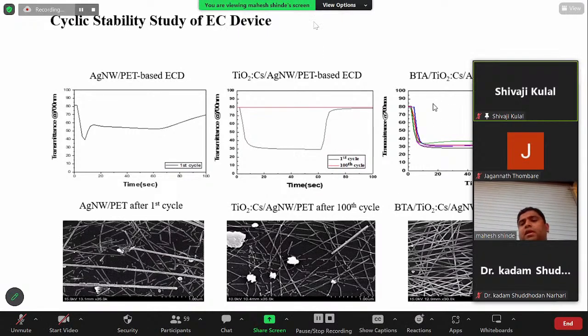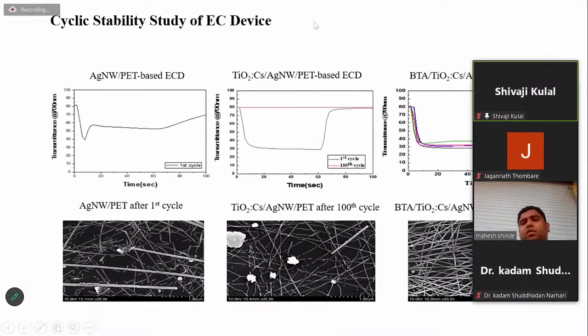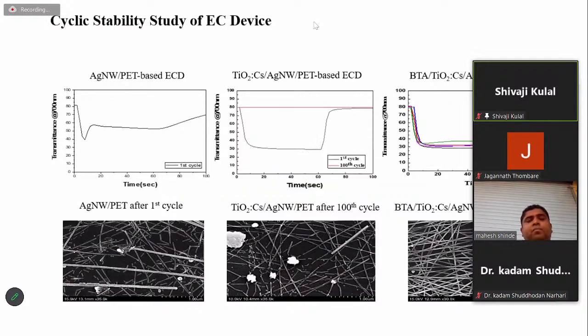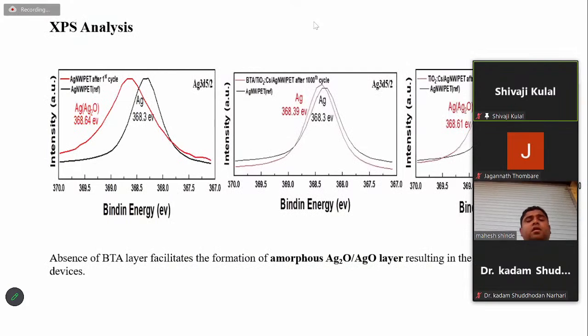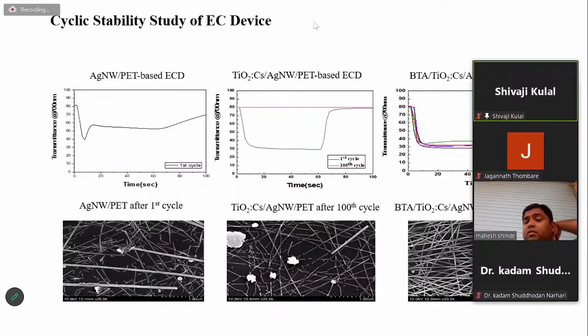But in the case of the BTA TiO2 CS, the corrosion inhibitor added silver nanowire worked for 1000 cycles, and you can see the stable silver nanowire network even after 1000 cycles. I also proved the role of BTA using XPS.